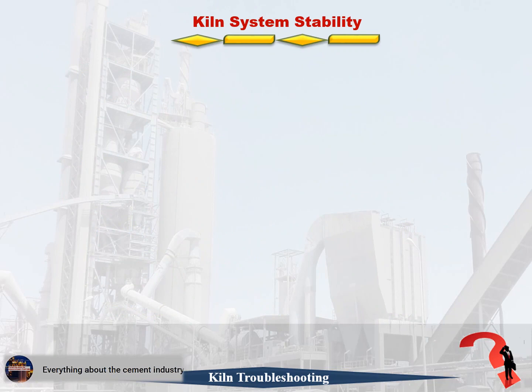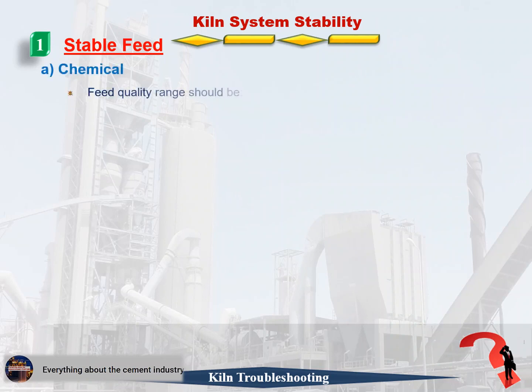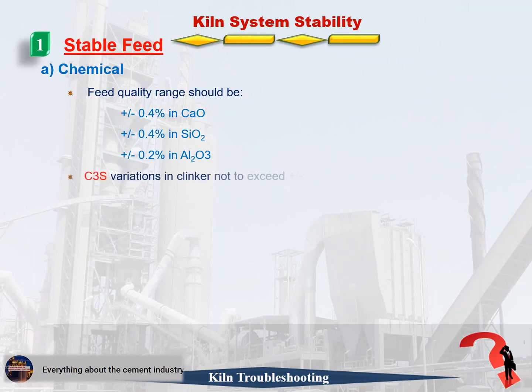Kiln system stability depends on 8 main factors. 1. Stable feed. It is divided into 2 parts, chemical and physical. A. Chemical. Firstly, feed quality range should be plus or minus 0.4% in CaO, plus or minus 0.4% in SiO2, plus or minus 0.2% in Al2O3. Secondly, C3S variations in clinker not to exceed plus or minus 3%.